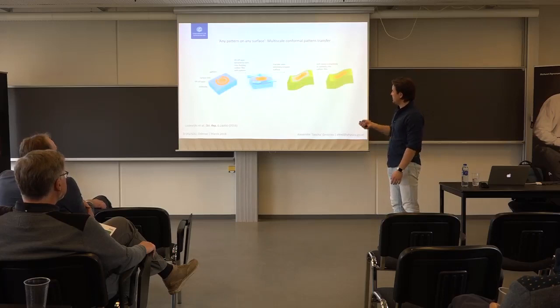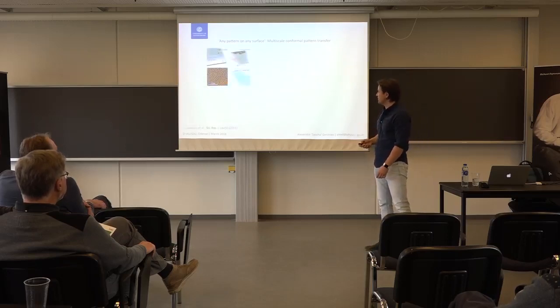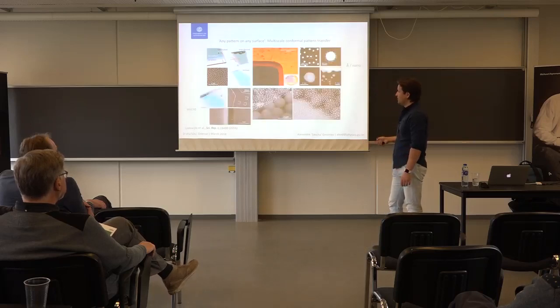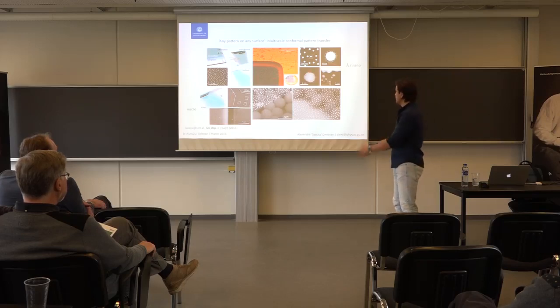It's a simple procedure that is again described in detail in this paper. You essentially use the sacrificial layer and you lift your structure and then you deposit it and then you remove the carrying film, and here you go. You can basically pattern PDMS fluidics. You can pattern glass, of course. You can pattern transmission electron microscope grids, where the supporting film, which is carbon, just carries your structures, and you can do analysis with atomic resolution.